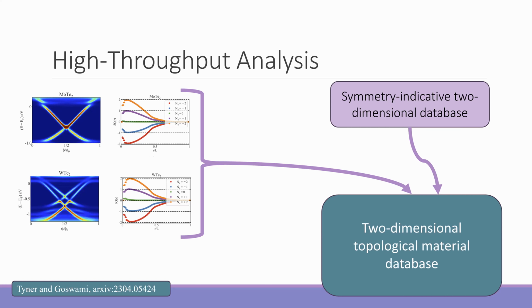So we did this screening, gathered up these materials, and then we also combined our results with the results of prior searches that had used symmetry indicators, EBRs, the typical methods to search for topology. What's different about this database is that we have a more strict criterion for what's trivial. A system only gets labeled as trivial if non-trivial band topology can't be found doing this flux tube insertion. So it's a different database in terms of what we're assigning as trivial. But it has some of these features we want to feed to our eventual generative model, because there's a lot of materials that have larger band gaps in there.